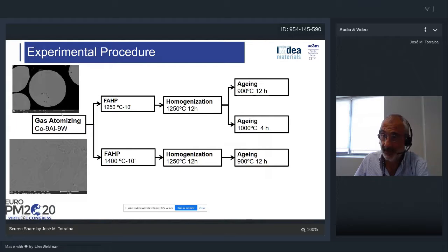We have gas atomized the cobalt-9 aluminum-9 tungsten. This is the microstructure of the powder. Then we have consolidated these powders by field-assisted hot pressing at two different temperatures for 10 minutes, applying 50 megapascals. And then we have homogenized the powders after 12 hours at 1250 degrees. And we also perform an aging treatment after the homogenization at 900 and 1000 in the case of the 1250 sintered material, and only 900 in the case of 1400 sintered materials.